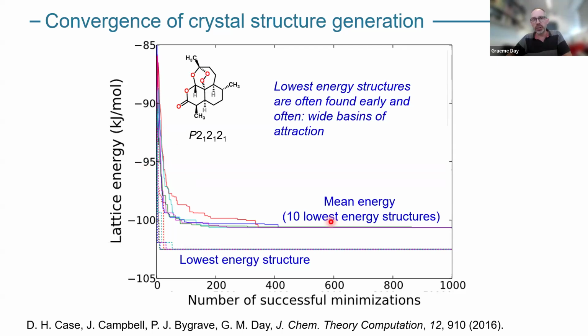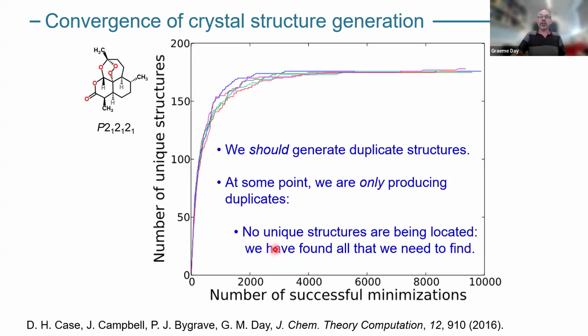If we look at the average energy of the lowest 10 structures, and now I'm interested in not just the lowest, but the lowest handful of structures, you see that converges after a few hundred. So this is just giving an idea of, depending on whether I'm really just interested in the lowest energy structure, or if I'm interested in finding all structures, how many structures I might need to sample within a particular space.